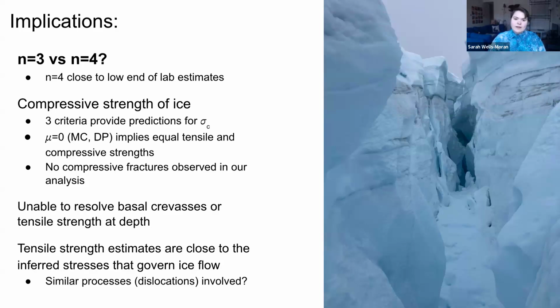Now, given that we didn't observe any fractures in the compressive regime, it's kind of impossible to say whether or not these predictions are actually accurate, but it is interesting to look at how specifically the value of internal friction impacts compressive strength of ice. In a lot of ice models, it's been set to pretty low values, which for the criteria we tested implies that the tensile and compressive strengths are very similar, if not the same, which is not often observed in nature. Usually the compressive strength is much larger than the tensile strength.